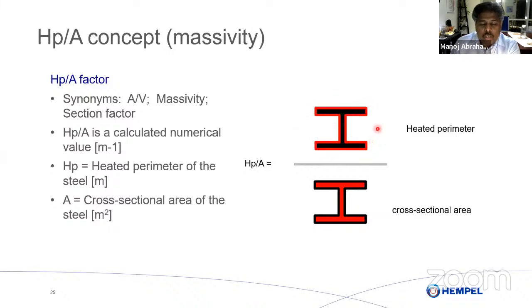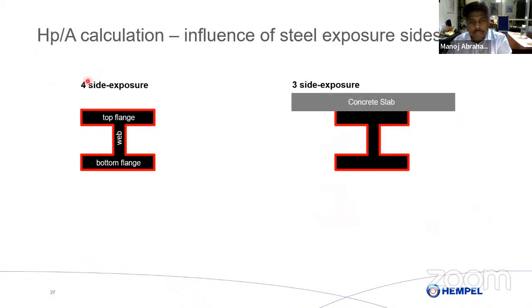If this, for example, is a column, all four sides are exposed to potential fire. So heated perimeter divided by the cross-sectional area, you get a certain number. Lower the number, lower the thickness. Higher the number, higher the thickness. So if the area is more, that means it is more massive, so your HP by A is smaller. So the thickness you can apply is smaller as well. So just a small calculation. As engineers, we like to do this calculation.